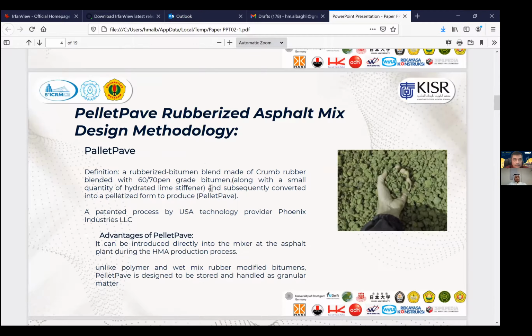First, the crumb rubber was blended with 60-70 pen-grade bitumen to produce a rubberized asphalt. Then this blend was converted into a pelletized form called Pellet Pave, as you can see. This process is patented by a USA technology provider called Phoenix Industries. One advantage of Pellet Pave is that it can be introduced directly into the mixer at the asphalt plant during the production process, as a partial substitute to the bitumen content.